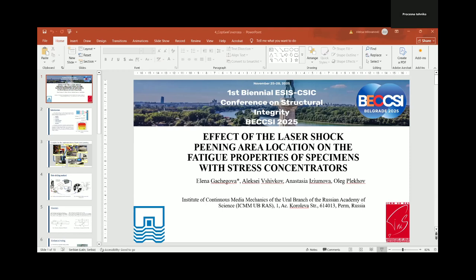Right after laser shock peening, we measured the residual stresses to understand what we have after using different laser shock peening zones. As you can see on the screen, we have a similar picture if you speak about maximum values of residual stresses and their depth for both schemes. So we think that at the beginning of the fatigue test, both specimens have initially the same residual stress state.